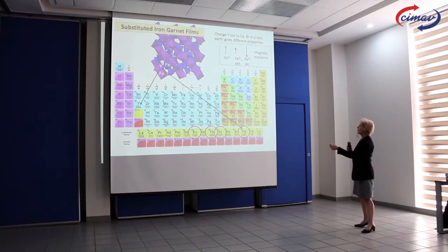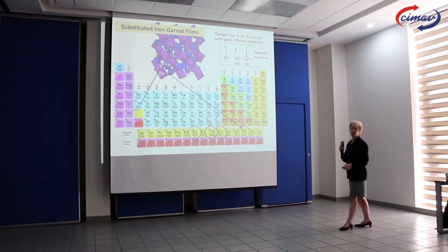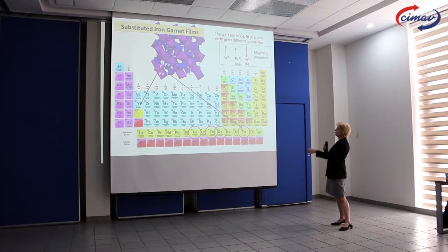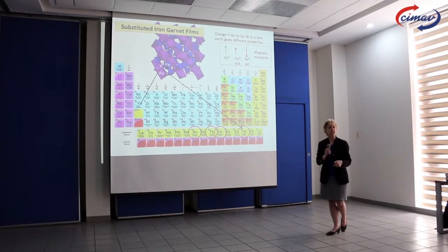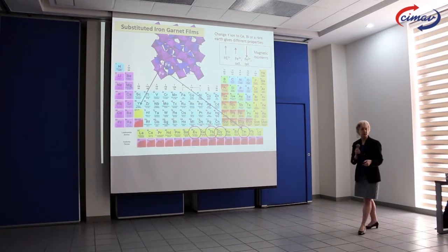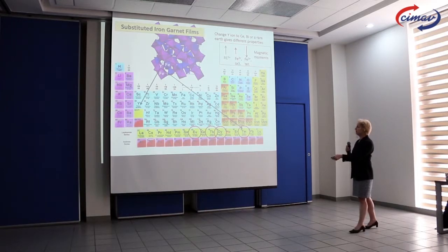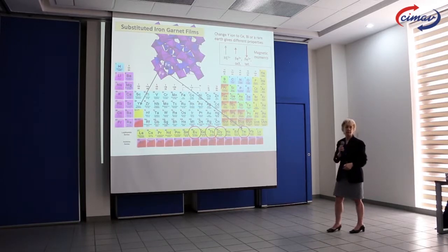And when we do that, thinking of the magnetic properties, the rare earth, which is also a magnetic ion, couples with the octahedral ion, and it's opposite to the tetrahedral ion. So now when we look at the magnetism of these materials, we have to consider the combination of the rare earth magnetism with the iron magnetism, and that can give us some different magnetic properties, particularly changing with temperature compared to what YIG does. In YIG, of course, the yttrium is a non-magnetic ion, so there's nothing here, and we just have the iron. But with any of these others, we get some magnetism that we have to take into account.